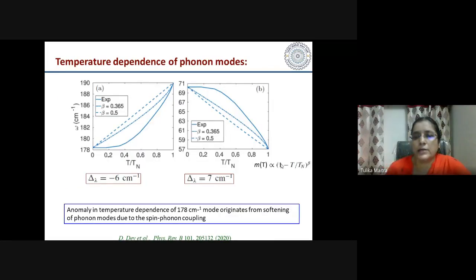What we have done here is that we have taken the temperature dependence of this magnetic order parameter as a function of temperature like this, where beta is the critical exponent. This is the mean field behavior, and this is the 3D Heisenberg model behavior, and this one solid line is the experimental one, and the shifts were calculated from the DFT. And then we calculated the new frequency, the temperature dependence of the phonon mode.